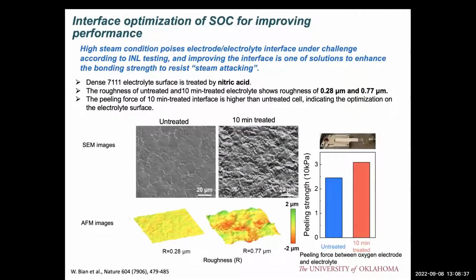And next one is the interface improvement. This is another piece of work conducted by our graduate student at Idaho National Lab. Here, very briefly, we use an acid method to corrode the electrolyte surface, because normally the electrolyte surface is very smooth. So when you fabricate another oxygen electrode on the surface, we have issues with easy delamination because they are very smooth. So we use acid to corrode the electrolyte surface to give a very coarse, very rough surface, and then we apply the electrode layer onto this surface.